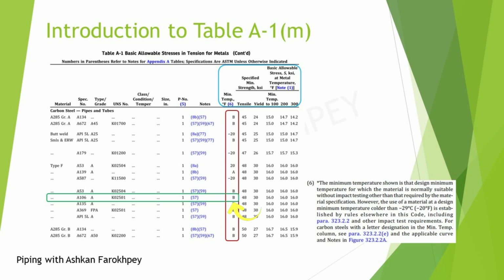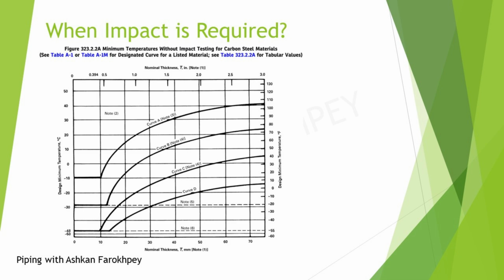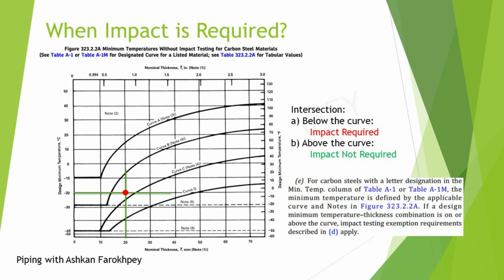When I see a letter, what I have to do is go into this figure and draw the lines based on my design data. Let's consider that my pipe thickness is 20 millimeters and my minimum design temperature is minus 20 degrees centigrade. By drawing the lines, we can see that the intersection point is below the B curve, and in this case, an impact testing is mandatory.